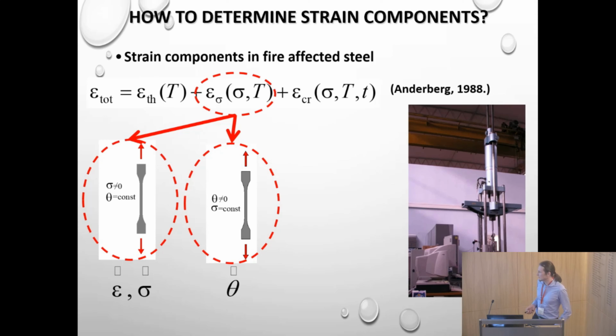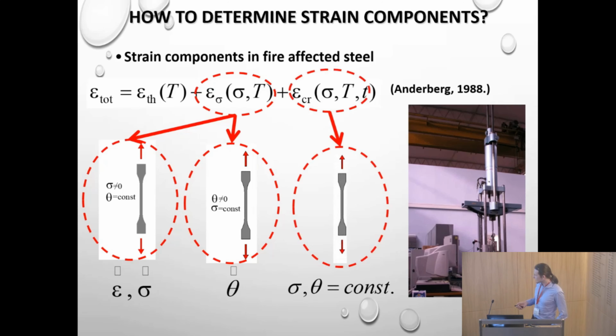And if we want to test the mechanical properties, we either do coupon tests, either by applying constant stress or constant strain rate on the specimen. Variation of that is to apply constant heating rate and try to determine the critical temperature and do subsequent coupon tests and recreate a stress strain curve which includes the creep component implicitly within that test. So there is a possibility of coupling these two strain components in that particular test, which is something that's used in structural codes.